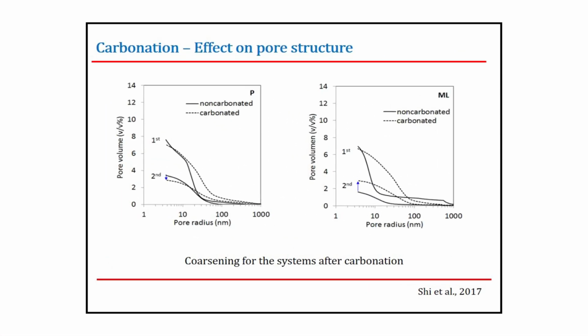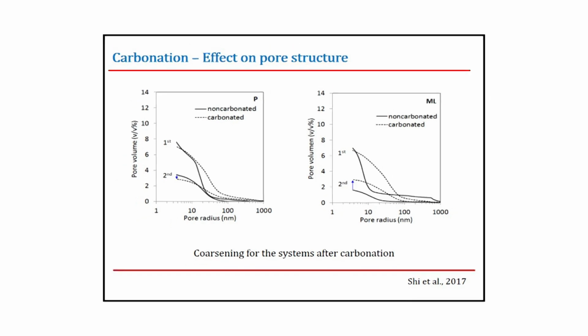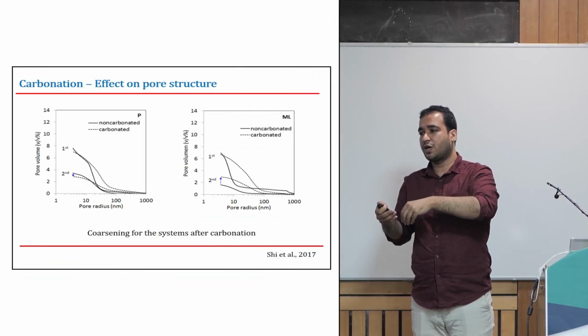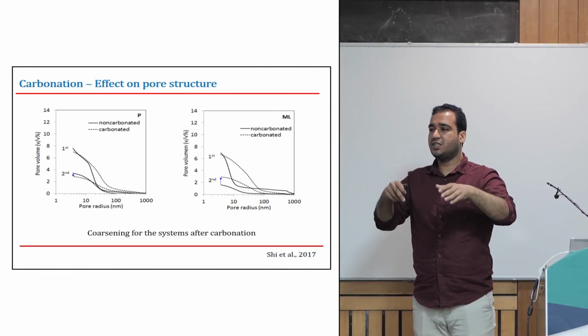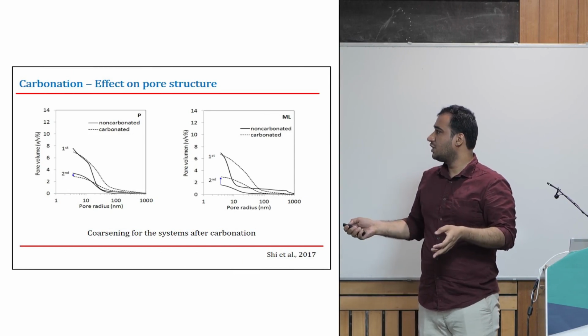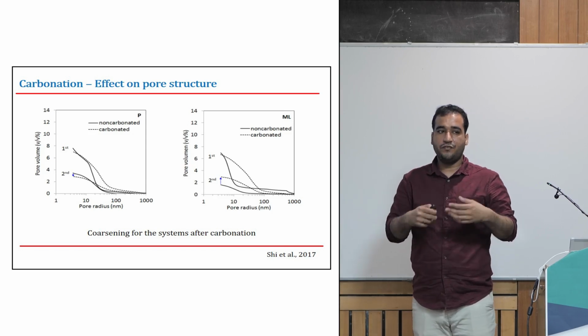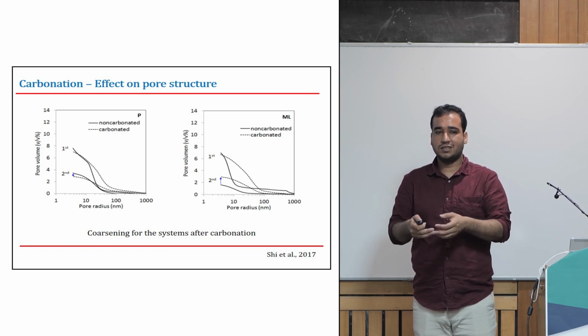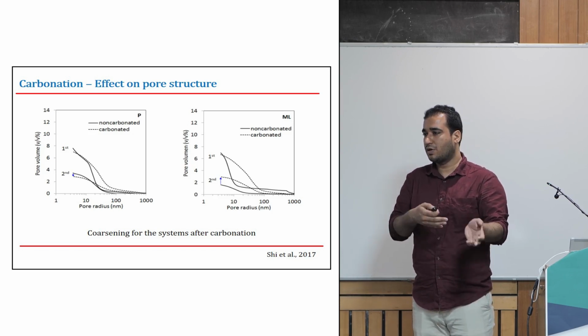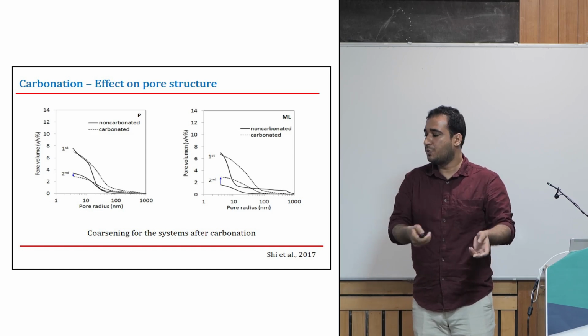Now, before I jump into the corrosion, carbonation has an effect on the pore structure itself, because you are dissolving the calcium hydroxides in the system, and these are solid before. When they dissolve, you are precipitating calcium carbonate, which is again solid. So you are changing the pore geometry of your structures. If you see for Portland cements, it leads to a coarsening, and for metakaolin blends, it leads to a coarsening again. So the effect of the carbonation on the type of the blend is similar to each other, be it for limestone calcined clay cement or be it for OPC, it's quite similar.